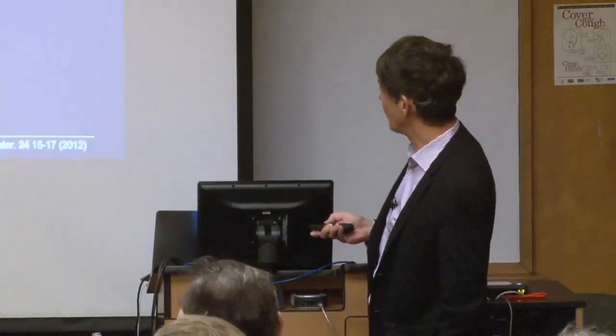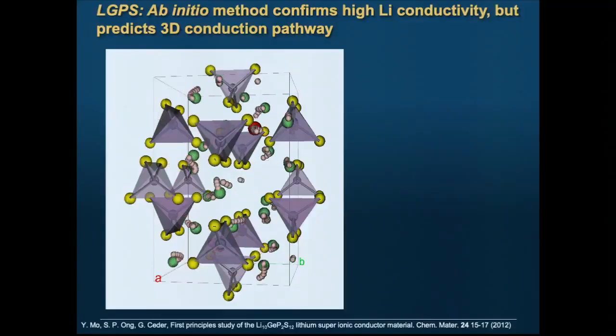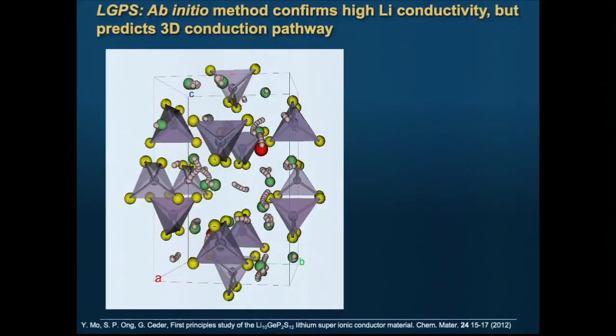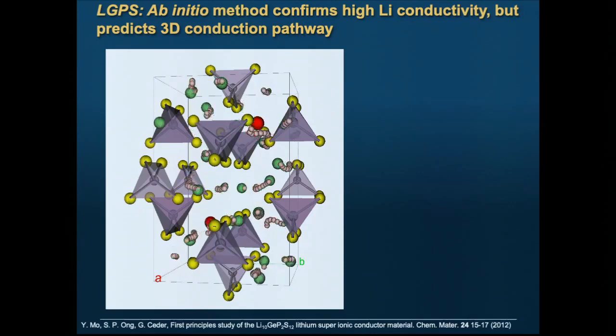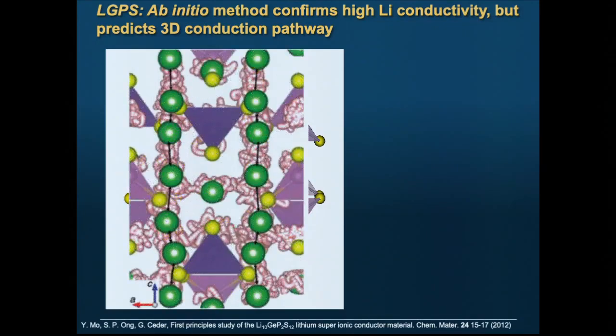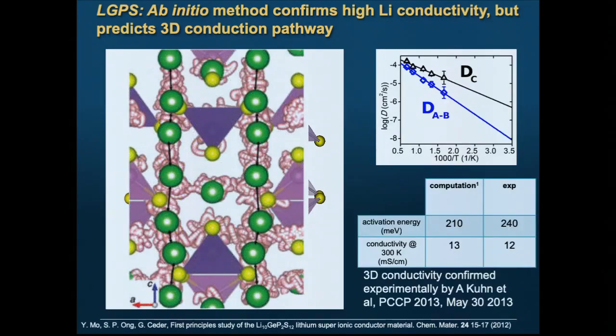We jumped on that right away and did initial simulations. This is just a pretty picture where we show that indeed you have very high conductivity. But we showed first of all, and this has been confirmed by others, that it's not a one-dimensional conductor, it's a three-dimensional conductor, because you have diffusivity in all three directions. And that makes sense. One-dimensional conductors are terrible because they have channel blockage. So even fast one-dimensional conductors tend not to operate in a macroscopic mode, because anytime you put a defect in the channel, it is completely blocked.